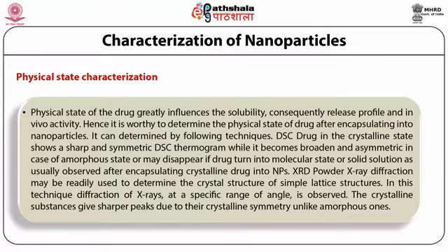Number 1 is DSC. Drug in the crystalline state shows a sharp and symmetric DSC thermogram, while it becomes broadened and asymmetric in case of amorphous state or may disappear if the drug turns into molecular state or solid solution, as usually observed after encapsulating crystalline drug into nanoparticles.